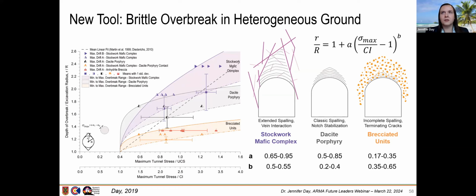So to address that, I looked at adopting some excavation damage zone depth functions from work by Matt Perras to have a general form for being able to pick your own coefficients that capture the data for these heterogeneous grounds. So in the stockwork-mafic complex, we have a lot of very persistent planar veins. And in the brittle overbreak observations at depth, we found there was a sort of extended spalling, very high overbreak and vein interaction, which resulted in overbreak above what would be expected with the homogeneous ground function.